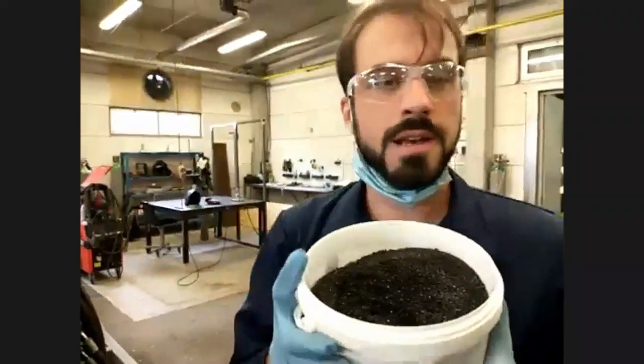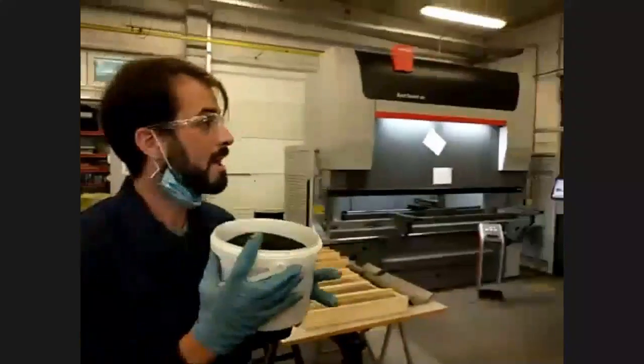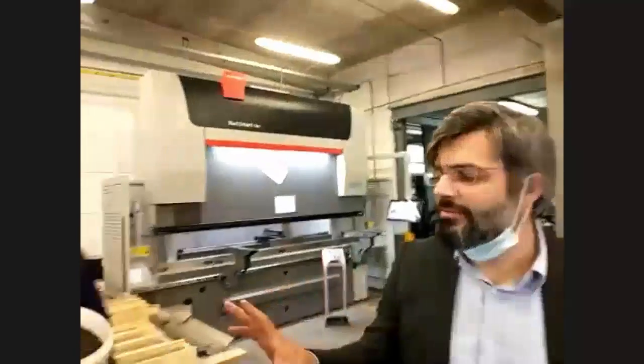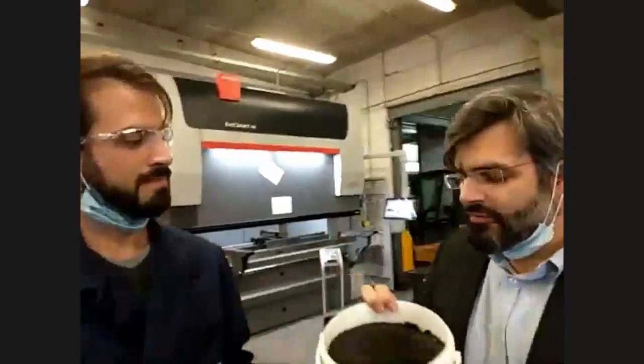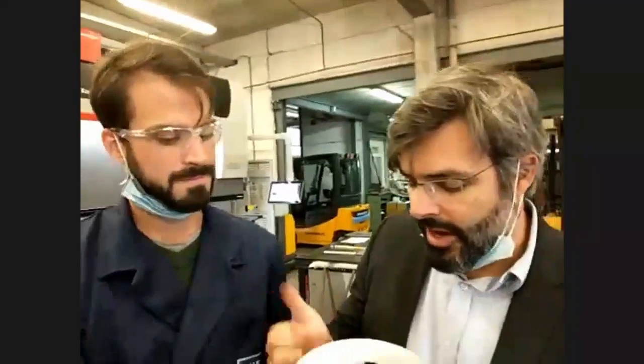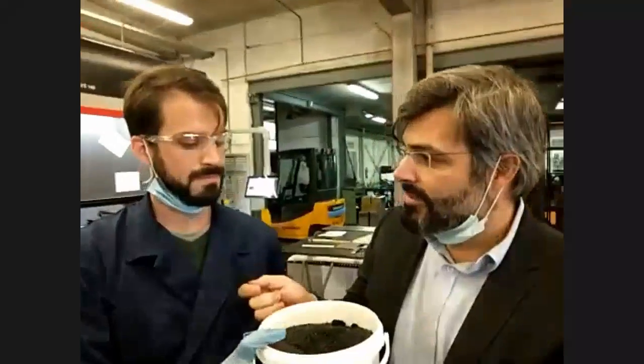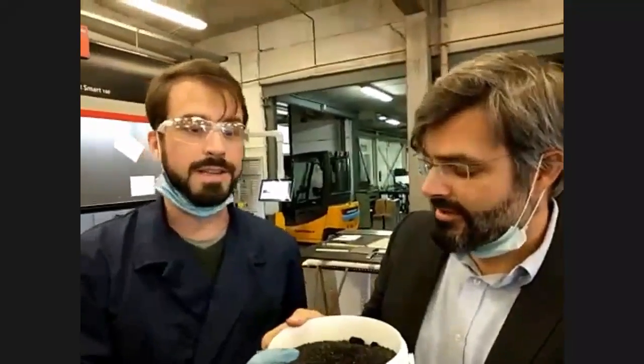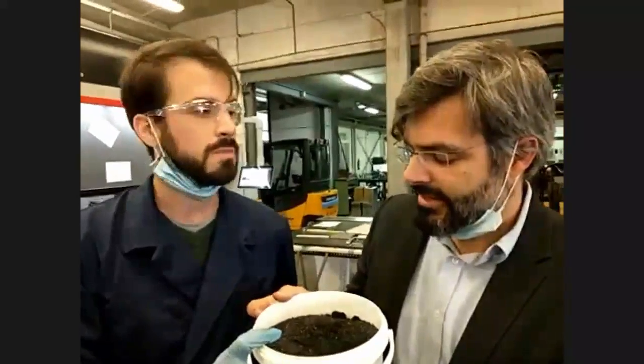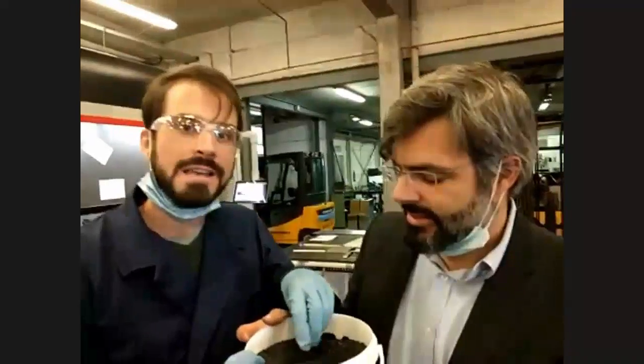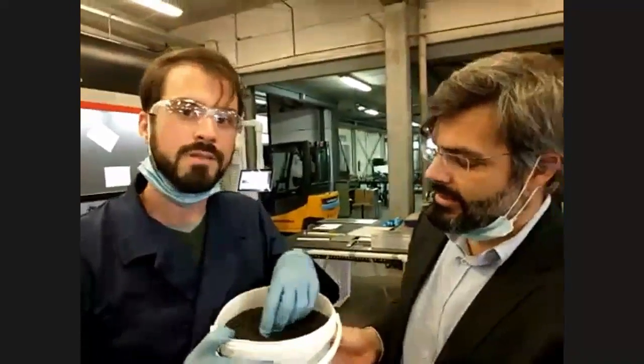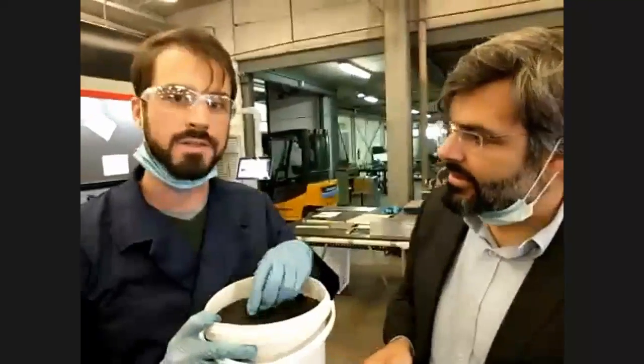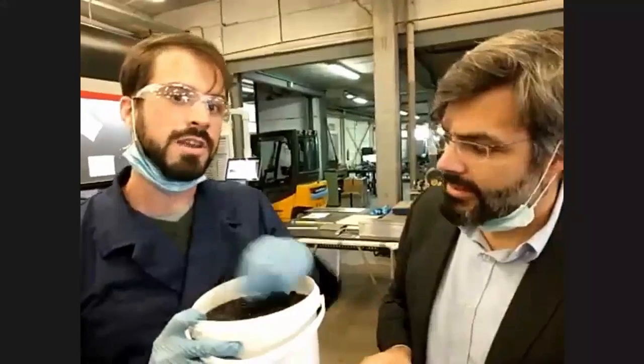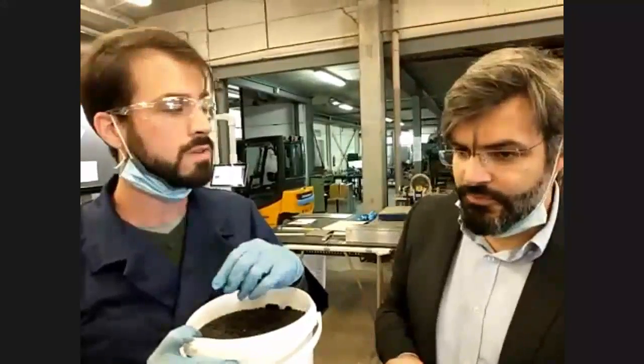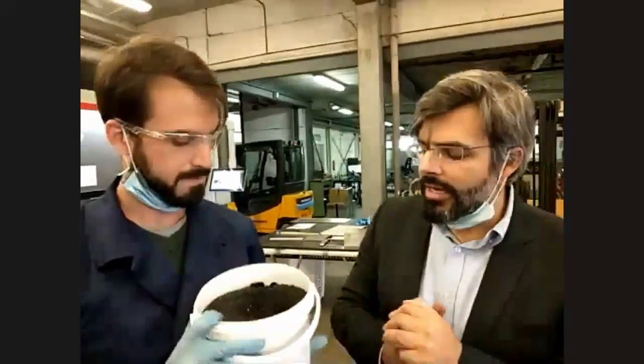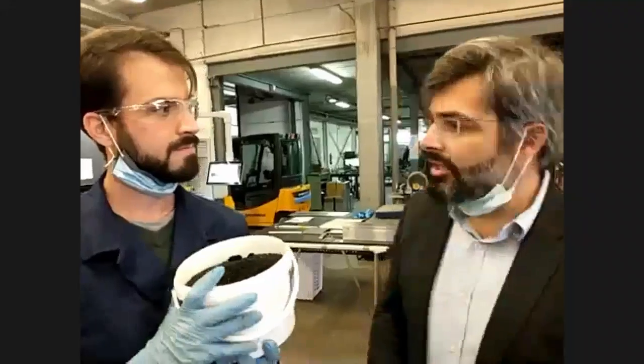So basically, Yannis, I can give you now the next material, which is a slag. Wow, wait. It looks nice, but let me understand a bit more. That for me is granular, and I want that into a binder. I want cement. I need it more fine. Yes, exactly, Yannis. The next step, what you need to do is you need to make this finer, because you can see that now it's relatively coarse still. So we get it relatively coarse out of the furnace, really like these granules. But the idea is now to go to another container where we make it fine, that it looks like a cement.